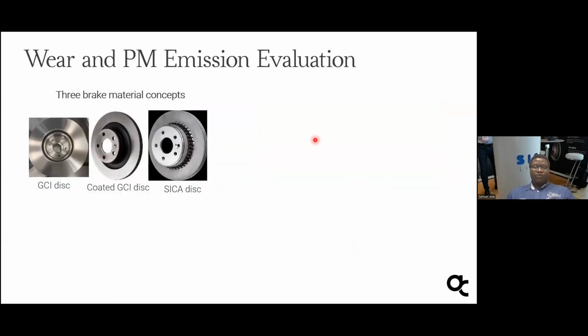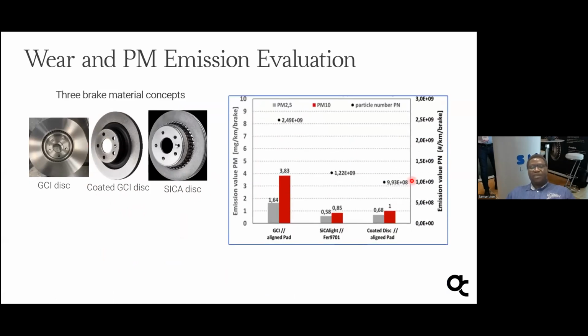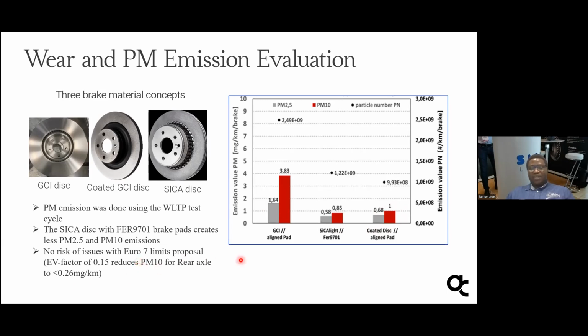We also evaluated the wear performance and the particle emission, using different material concepts: the GCI, the hard-coated GCI and the SICA disc. Based on that, the results were plotted using the WLTP procedure. From here, we see that the particles generated from SICA are comparable to that of the hard-coated GCI disc, which is very, very low. We also see that the PM10 is almost 78% lower compared to the GCI disc material, which means Euro 7 requirements will be easily met by this friction couple.